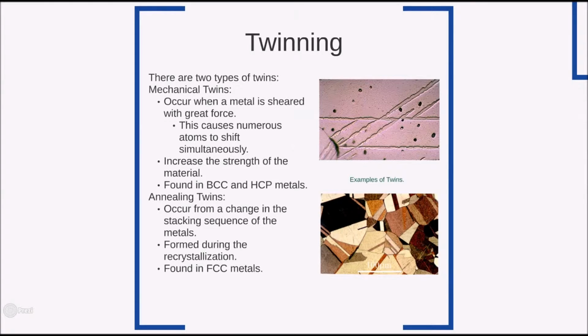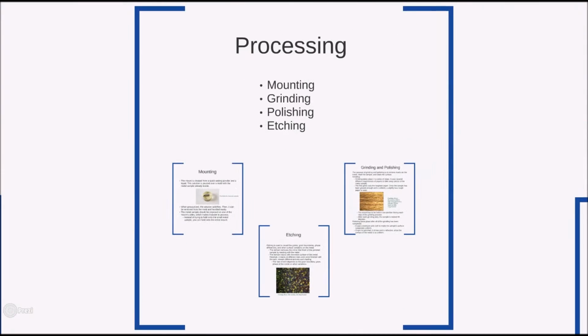Annealing twins can occur during the recrystallization phase of annealing. To achieve a more favorable orientation, a stacking fault can occur within the grain. This stacking fault can be seen in the metallograph and looks like a set of parallel lines. This type of twinning can occur in FCC metals.